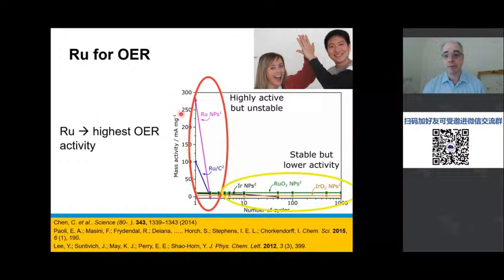But the problem is that they really have almost no stability. So on this axis here, we have number of cycles, and this is actually a log scale. So when you're cycling these ruthenium nanoparticles after even just 1 or 2 cycles, essentially the ruthenium catalysts are just dissolving up into the acid electrolyte.